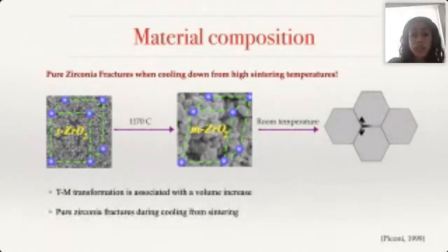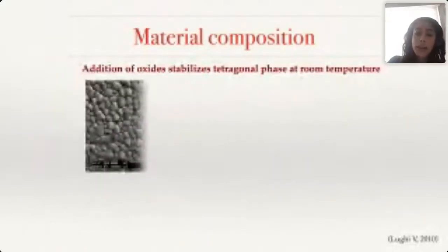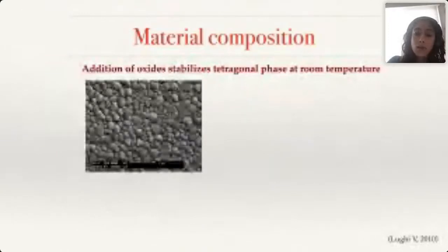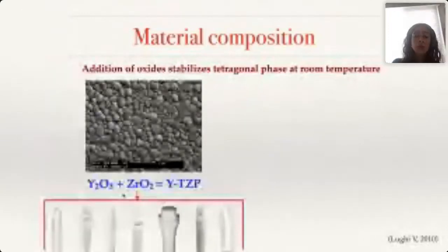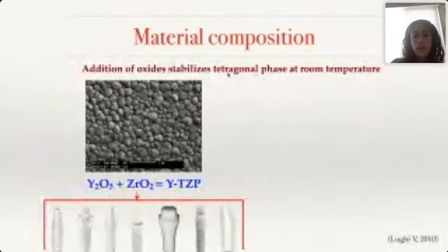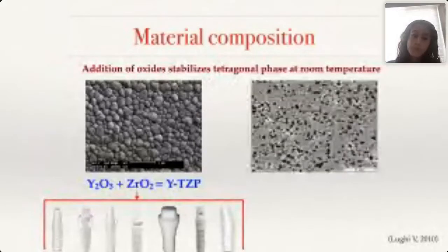That's why, to fix this issue, they've added an oxide to the material. So the current material isn't just zirconia — a little yttria is added so the grains are stabilized at the tetragonal phase, and we won't have issues with grain and crystal phase changes at different temperatures.